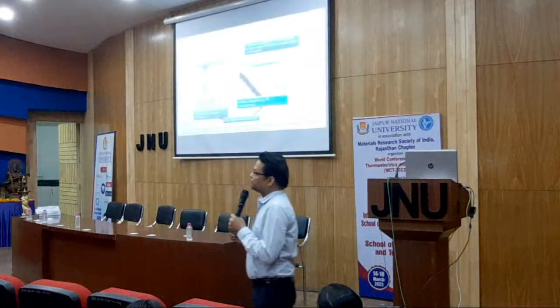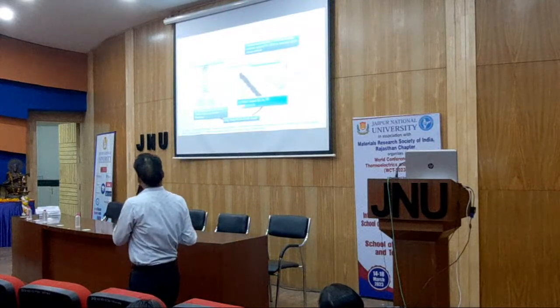Graphene oxide and reduced graphene oxide cannot be utilized directly, but these can be doped with bismuth telluride, or you can make a new nanocomposite where the graphene improves the Seebeck coefficient and electrical conductivity. At the same time, by phenomena such as phonon blocking, you can reduce the thermal conductivity, right? This is the approach we have taken. We synthesize the bismuth telluride nanomaterial by a calcium-assisted method. Then when you coat it with in situ doped graphene, the material makes a different kind of morphology. I will show you TEM and FESEM images, right?